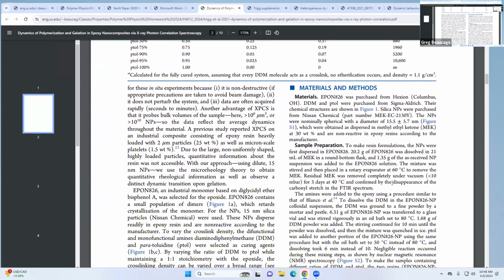So what they did that was really smart was they took silica nanoparticles with a diameter of about 15 nanometers in the system. I forgot to mention the fillers in our material were about micron size. So orders of magnitude larger than those nanofillers. This is really nice because now we're on that length scale where the XPCS is actually picking up interesting Q dependence, right? A Q space and real space is like 1 to 100 nanometers, something like that. So you're really now actually probing that individual silica particle moving around in the matrix, whereas we were kind of looking at these huge fillers just floating around.